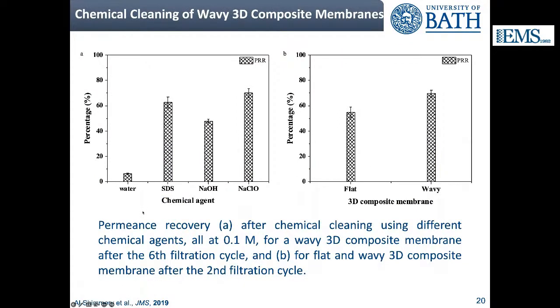What we also did is to look at some cleaning agents. As I mentioned, the data I've shown you before is only using water as a cleaning agent. We were able to recover only part of the irreversible fouling for the wavy membrane, even though that was a very small component. We then tried some common cleaning agents, and it was possible to recover a significantly higher proportion. So by using a wavy membrane and a cleaning agent, you can go pretty much to almost initial permeance.